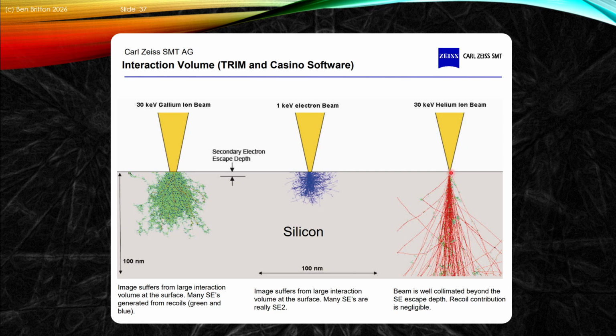Now, those helium ions can travel quite far into the material, and so you can actually get quite a lot of, say, transmitted or incident damage. Relatively low damage per unit ion, but there will still be a little bit of damage from the helium going into here.